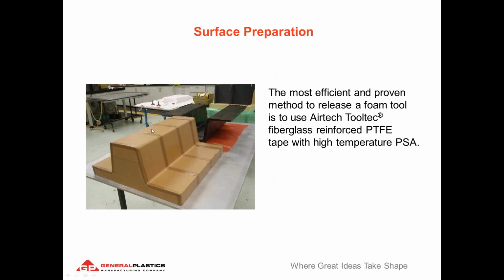So we'll move into a little different shape tool, and the most proven and efficient method to release a foam tool of lower density, which of course has higher surface porosity, is using a product from Airtech called Tooltec, which is a fiberglass reinforced PTFE tape with a pressure sensitive adhesive on it. For example, a large 100 square foot surface area tool with 2 or 3 people working on it can be sealed up in about 15 minutes, versus a couple of days with a filler and sealer method by the time you get it all sanded to your desired finish.